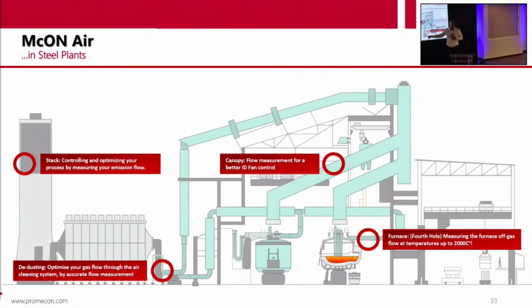On this side, again, I could have another presentation on that. We have developed a system that can measure the flow out of the furnace and that can measure the gas composition out of the furnace. So we can tell you how much CO and how much CO2 comes out of this furnace. Why is this important? The operator of the furnace can see how much carbon comes out of his furnace, and he can reduce the power on time of the furnace.